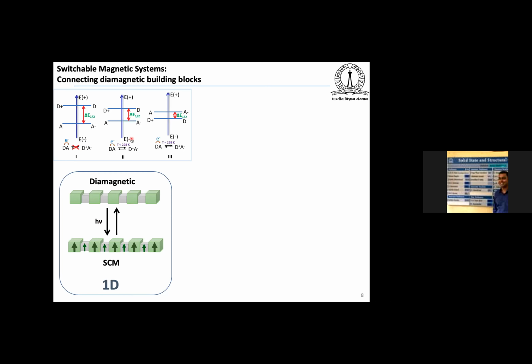Also, another important thing you have to check, you have to adjust the redox potential between the metal centers, because metal to metal electron transfer is governed by the redox property change of the donor and acceptor. If the donor and acceptor ligand potential difference is very high, you will never observe the reversible electron transfer. If it's too low, immediately the electron transfer will take place, but it will not go to the reverse effect. So you need to adjust the redox potential between the donor and acceptor. So what we have observed is that if we can modify this donor and acceptor redox potential to roughly around 1 volt, then you can get the reversible electron transfer.